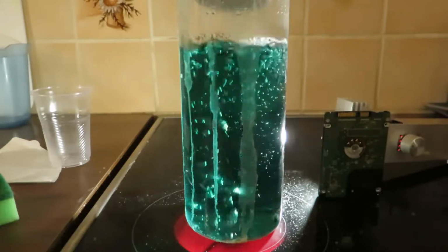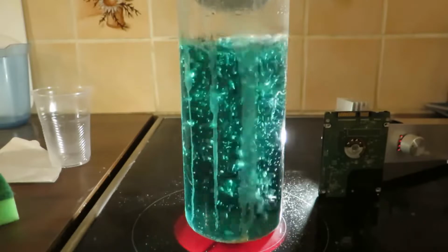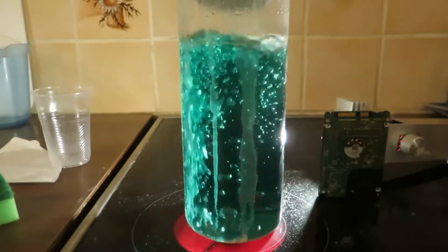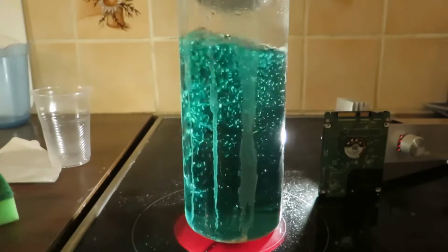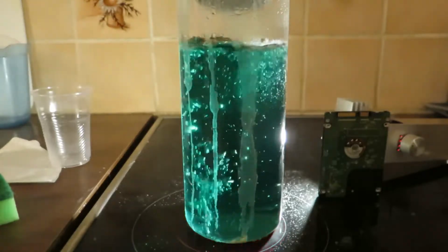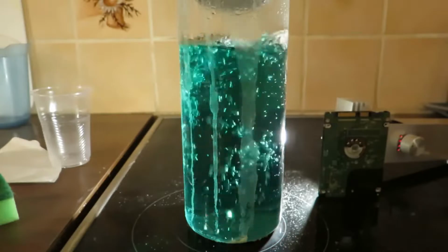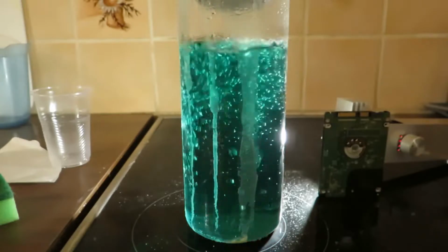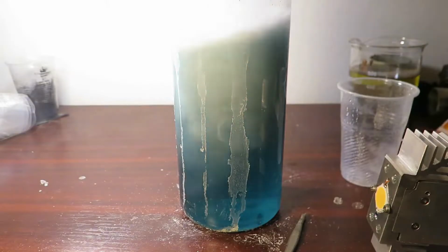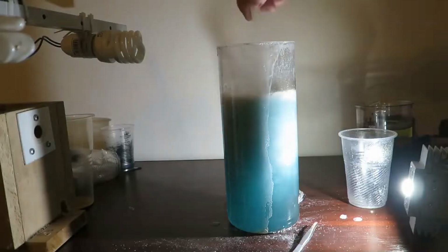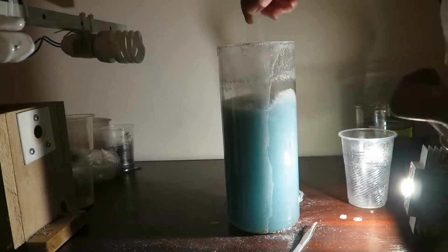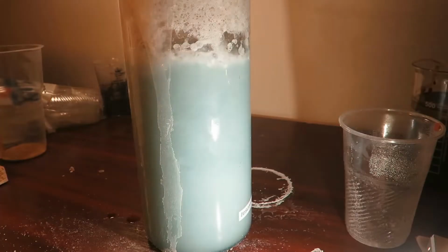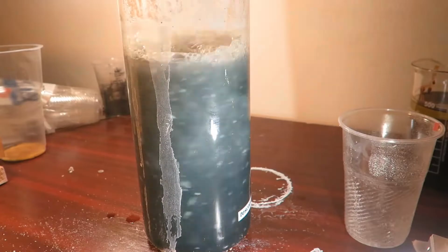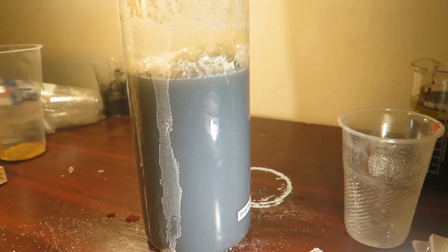And that is precipitation and cleaning of the chromium salt. It seems that chromium carbonate is the only thing that is really practical and insoluble, so we will go with that. You can precipitate it with sodium hydroxide or ammonia, but you will eventually lose some chromium there. So I am adding sodium bicarbonate to the solution. When the reaction is done, large flakes of chromium carbonate will start to form. You can simply filter this off and clean it, and that's quite a pure salt of chromium that you have there.